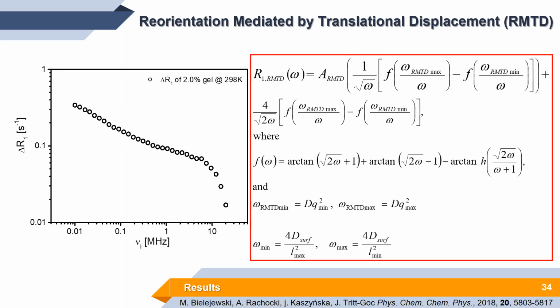If we go more into the details of the RMTD model, which I will not do at this moment, we arrive at some important parameters. And among them, there are two which can deliver us information about how the translational motion looks on the surface of the gel matrix. And this is the so-called surface diffusion coefficient, and also the Lmax parameter, which describes the maximum distance at which the molecule is traveling on the surface. So now we focus on the low frequency range of the NMRD profile.